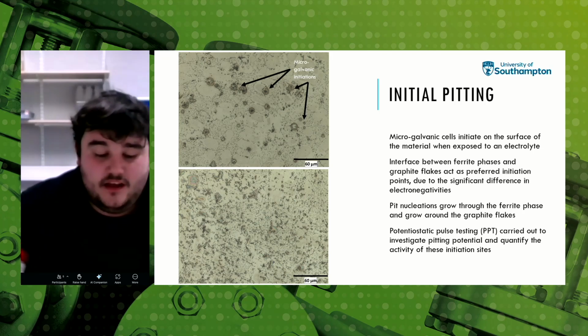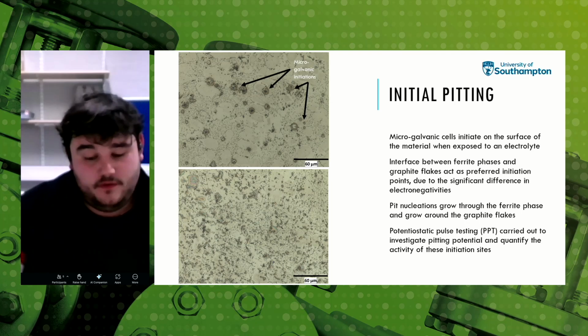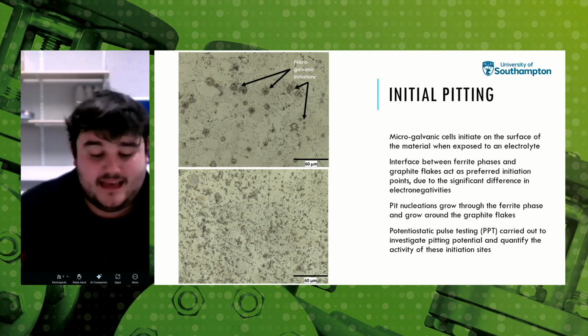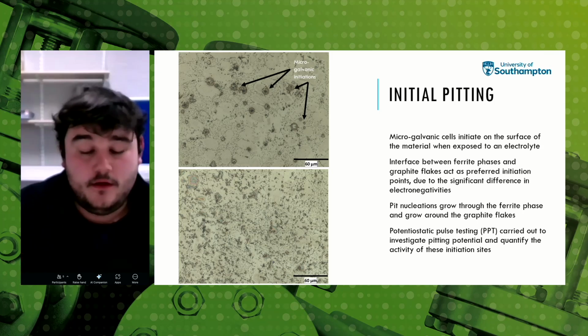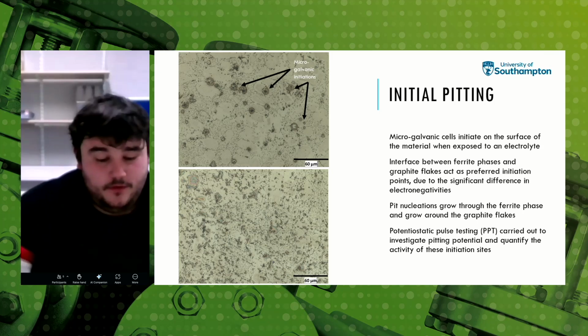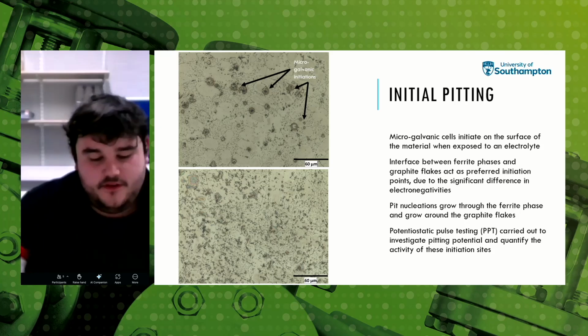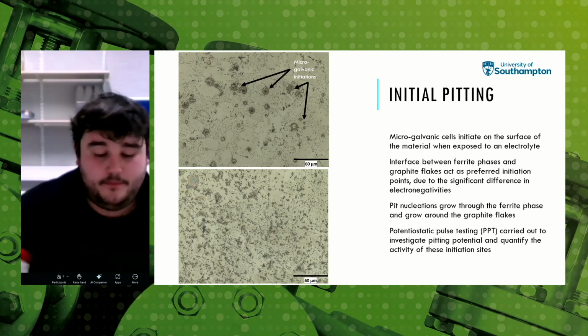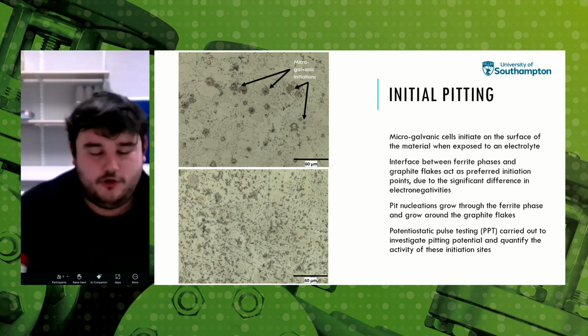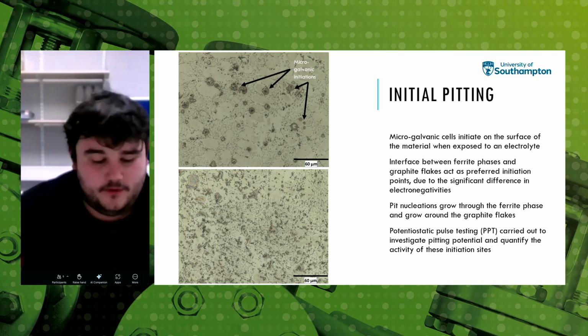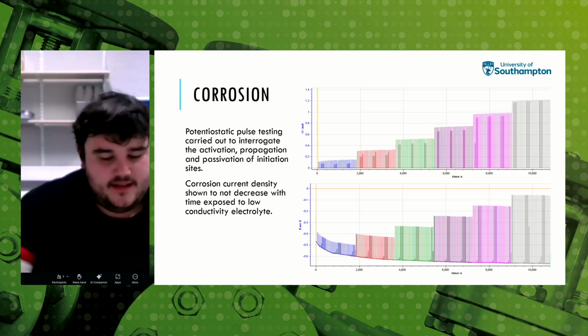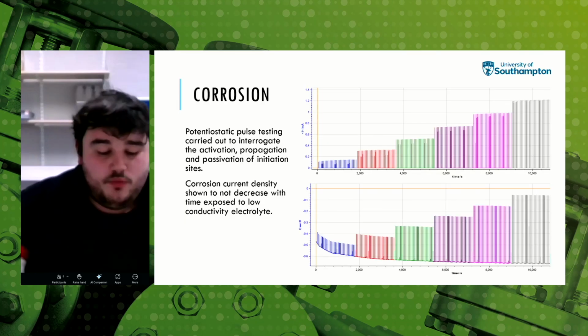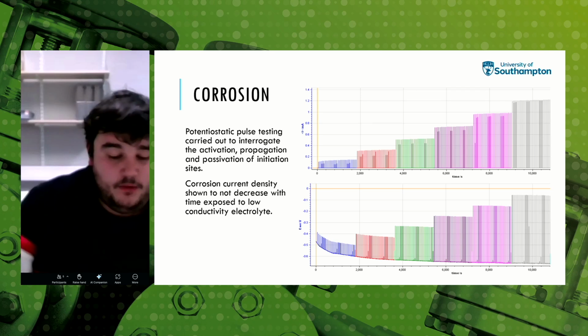And they preferentially initiate at the boundary between the different phases and begin to propagate eating through the ferrite, as the ferrite acts as the anode and the graphite acts as the cathode. So to explore these first initiations, we've carried out some potentiostatic pulse testing, to quantify the activity of these sites, and understand the potentials at which they begin to initiate and propagate. Next slide, please.